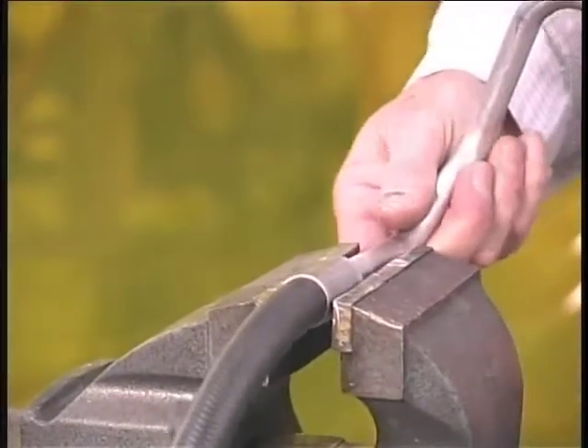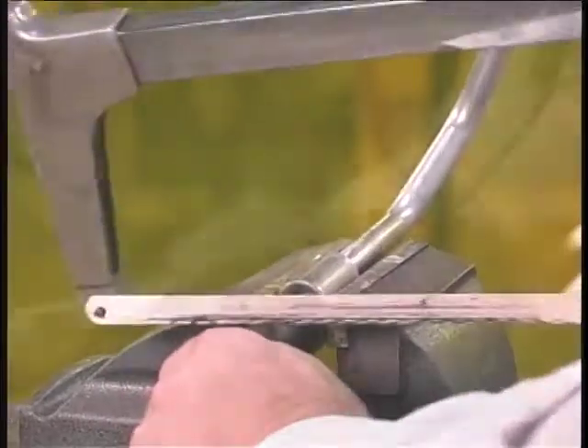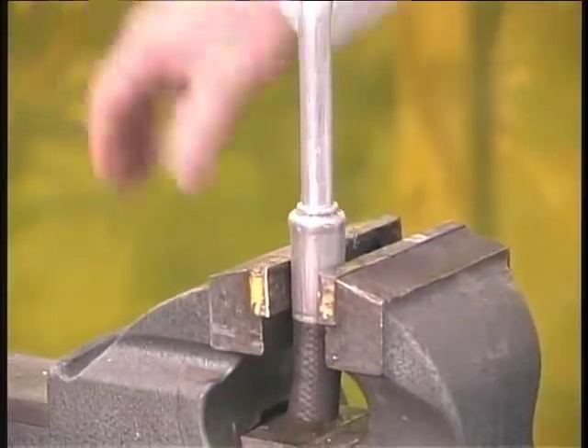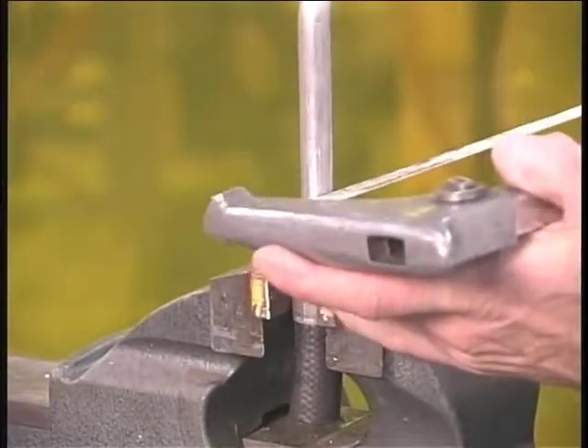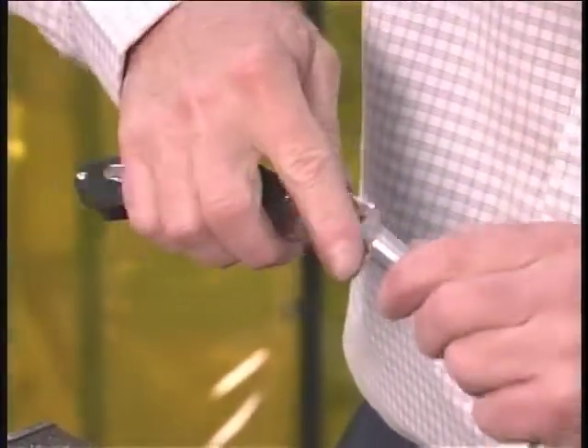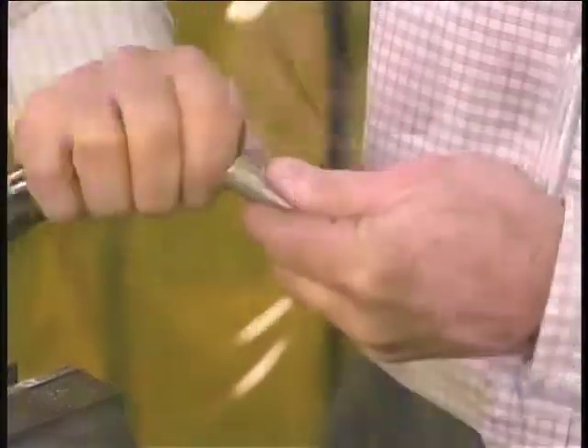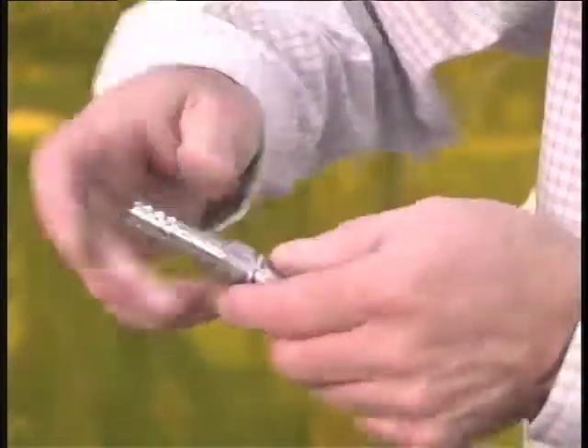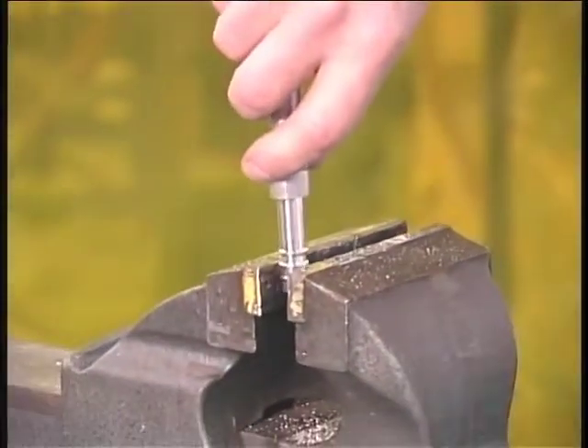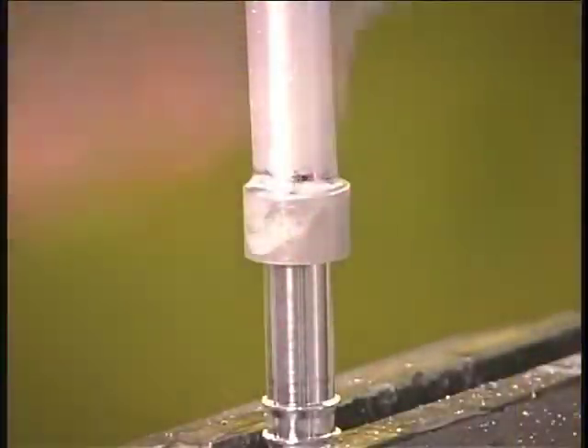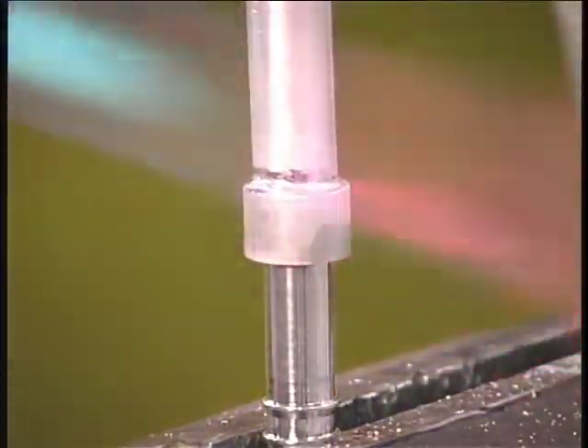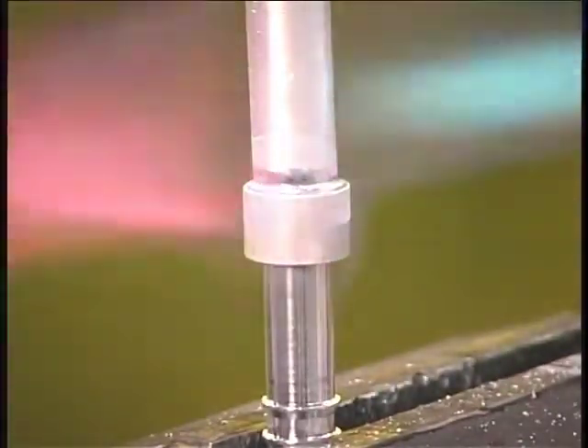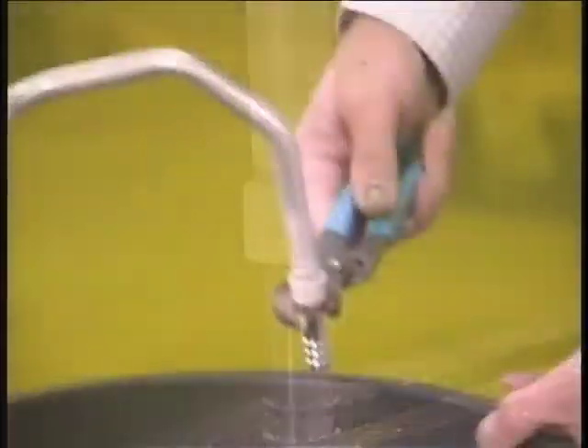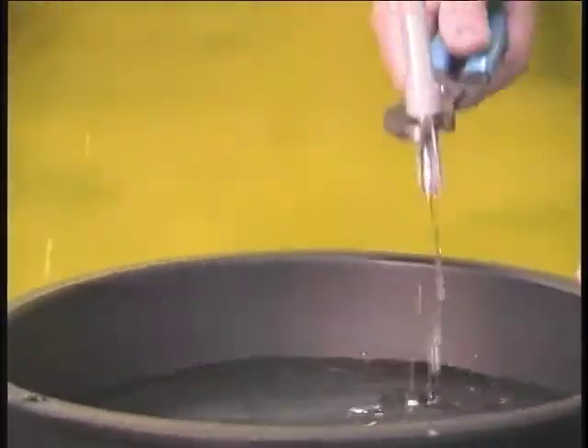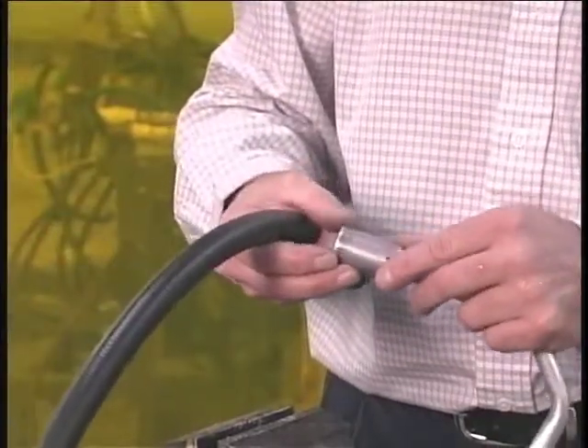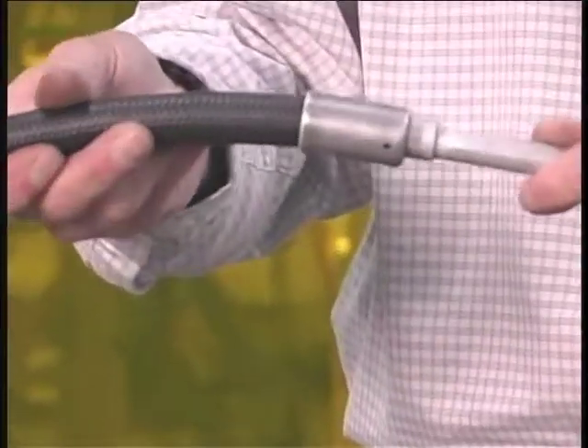Hoses generally leak just beyond the ferrule. Properly fixture the hose and cut it. Fixture and cut the end tube just beyond the ferrule. Chamfer to smooth edges. Clean and place the braze ring on the tube with a new barb end. Braze the joint, and cool in water. Slide the new ferrule over the new barb end, and then slide the hose into the ferrule. You are now ready to crimp the hose to the ferrule, completing your repair.